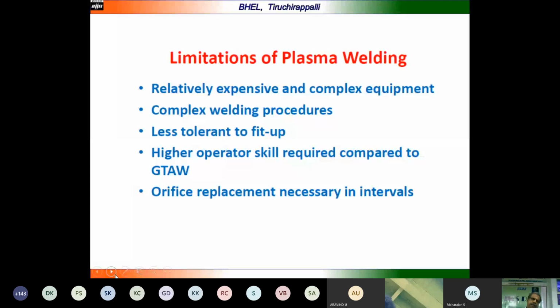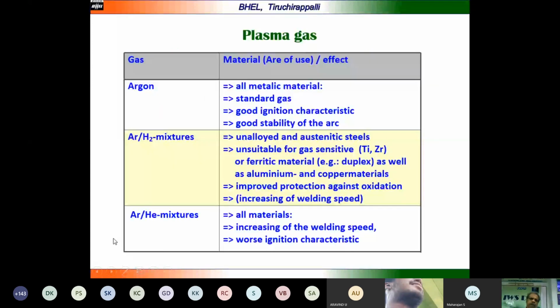Plasma gas can use argon-helium mixtures or argon-hydrogen mixtures, depending upon the application. For all metallic materials, argon can be used. The argon-helium mixture can be used. The argon-hydrogen mixture can be used for unalloyed and austenitic steels.